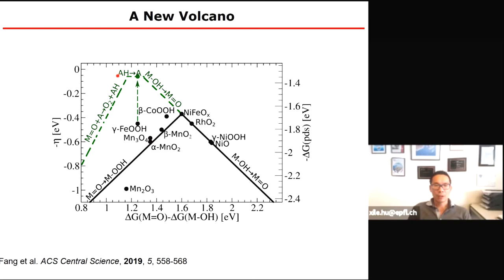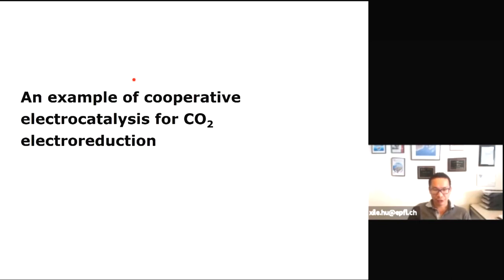Now, the third component of this volcano is the regeneration of the hydrogen atom acceptor to come back, and this has an energy of 1.3 eV, so the overpotential is about 0.1. And so with that, we can have the so-called new volcano plot with cooperative catalysis, where you overcome the limitation of the previous volcano plot by having bifunctional catalysis. We think this cooperative two-component catalysis can be really useful to overcome the limitation.